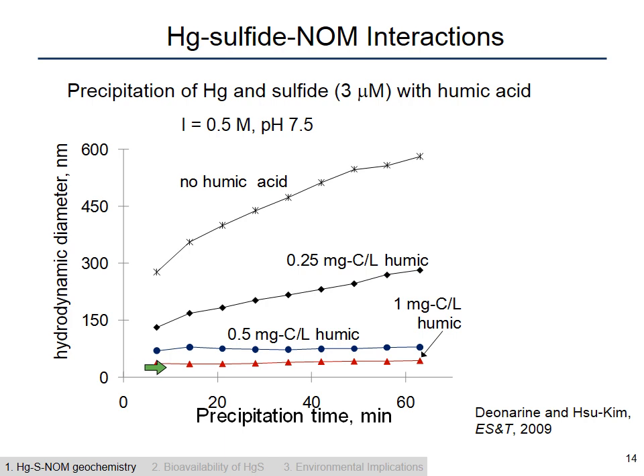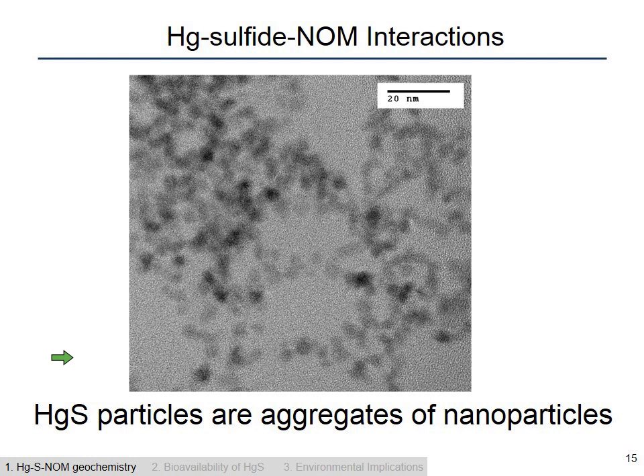that grow more slowly over time with increasing humic concentration. And with enough humic acid, you get particles in terms of the hydrodynamic diameter that are very small, less than 100 nanometers in diameter, and stable in solution. The kinds of particles that you're forming are actually aggregates of very small nanoparticles. So this is a TEM image of one of the solutions I showed on the previous graph. The image basically shows fairly amorphous nanoparticles of about 5 nanometers in diameter, and they are aggregated.